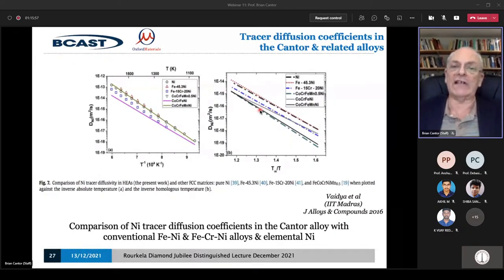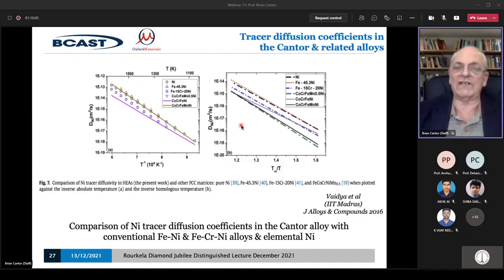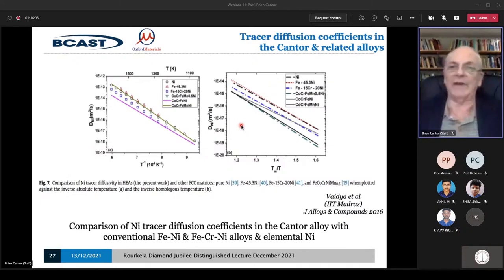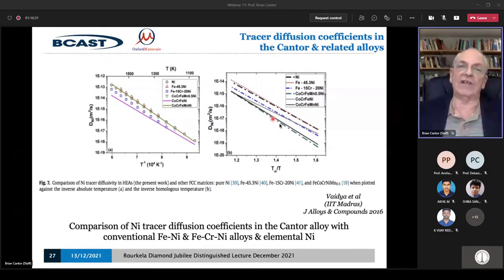It's quite hard to measure these results. The reason is, to measure diffusion coefficient, we normally weld two materials next to each other, see them diffuse and measure the composition profile. But unfortunately, if you have a multi-component material, those composition profiles are very complicated, and it's very difficult to extract the diffusion coefficient. You have to do what's called tracer diffusion experiments. They're much harder to do, but they're the only really good ones you can do. Not that many have been done, but it's been done now for quite a lot of different Cantor alloys. And consistently, you find about an order of magnitude slower diffusion. So the atoms move around more slowly.